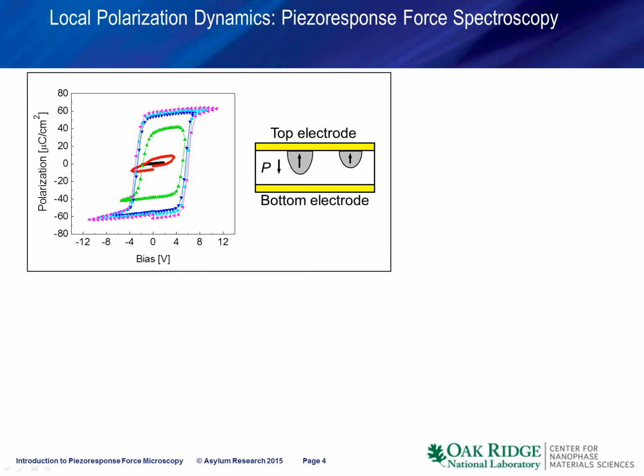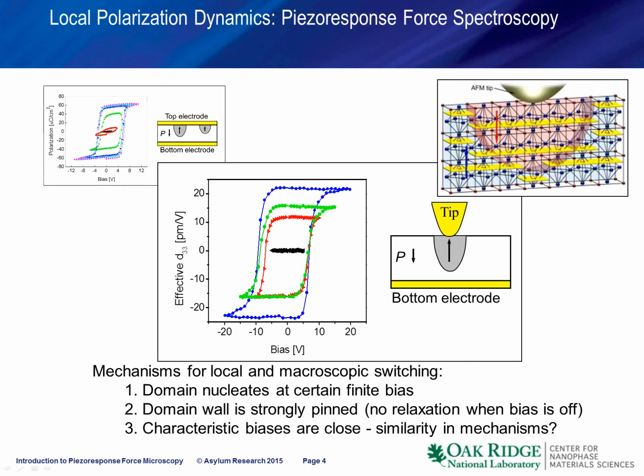Shown on this slide is an example of a classical macroscopic piezoresponse loop on a bismuth ferrite film. You can see that for small bias, the hysteresis loop is closed. For larger bias, it starts to open up, then it opens up more, and then it opens up and saturates. And we know that in this case, the hysteresis loop is the result of multiple domains nucleating, growing, and interacting with each other. In comparison, this is an example of a local hysteresis loop obtained using PFM. And qualitatively and almost quantitatively, it behaves exactly the same way as the macroscopic loop.